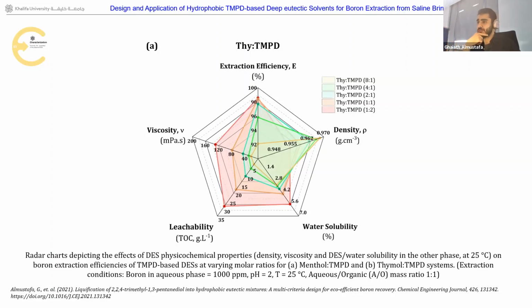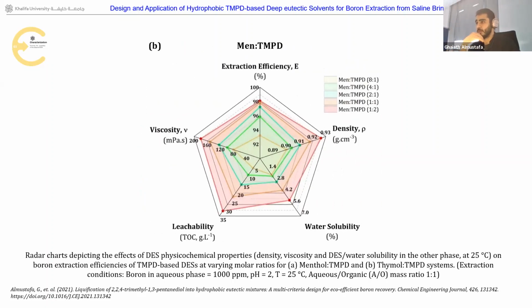Both density and viscosity, for example, or at least viscosity and leachability, increase with the higher ratios of TMPD, which we want to avoid. Viscosity specifically governs the mass transfer rate, and the leachability governs how much loss of DES that we have. The same thing can be said for the menthol TMPD system. With the higher TMPD ratios, we're getting an amplification of these critical aspects, the leachability and viscosity.